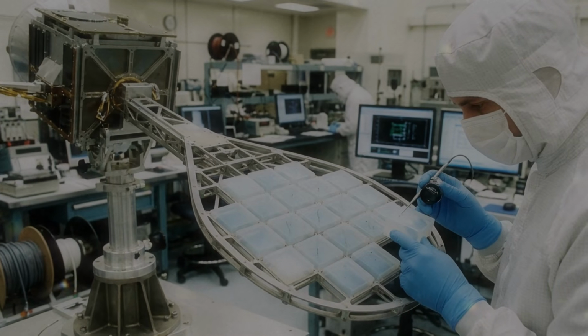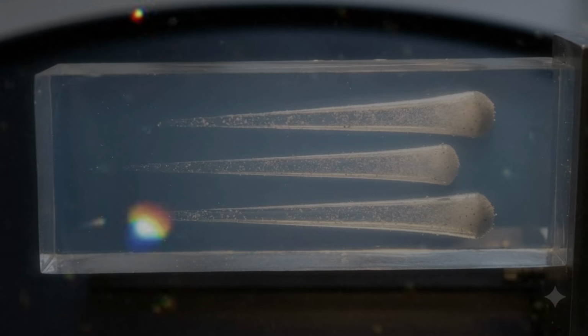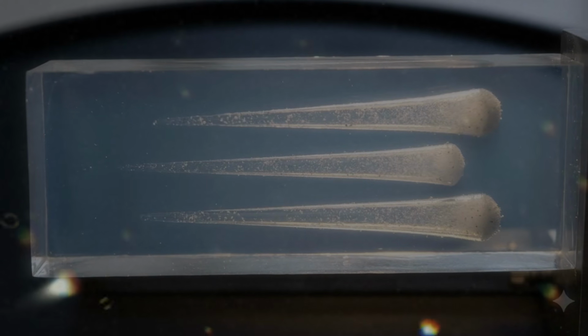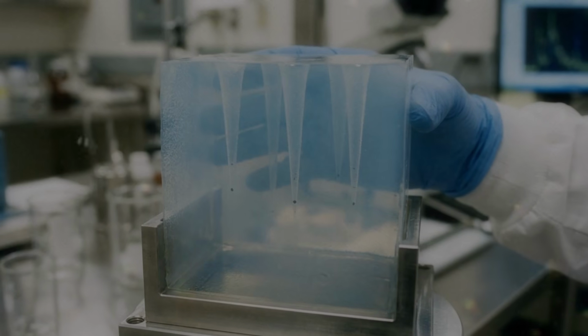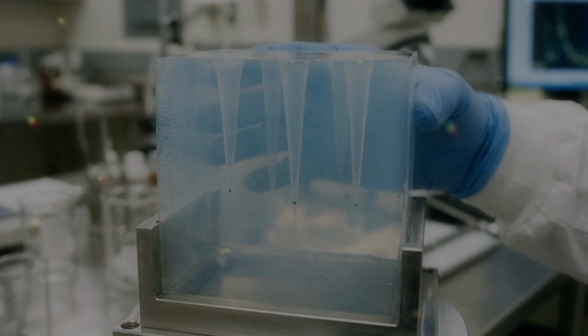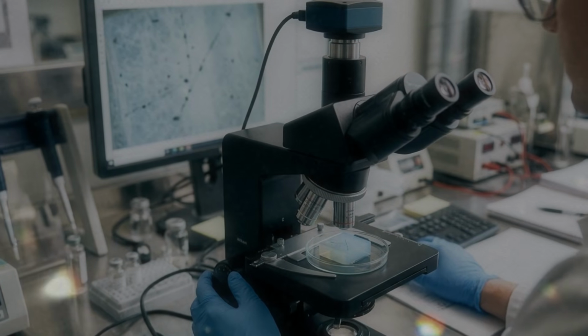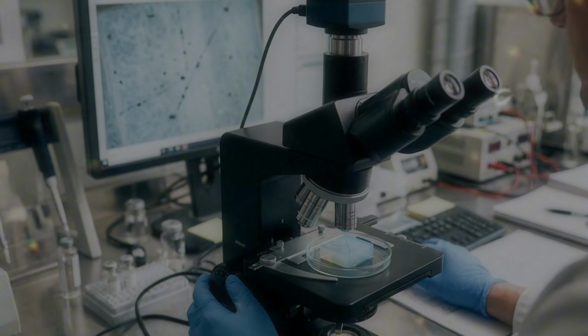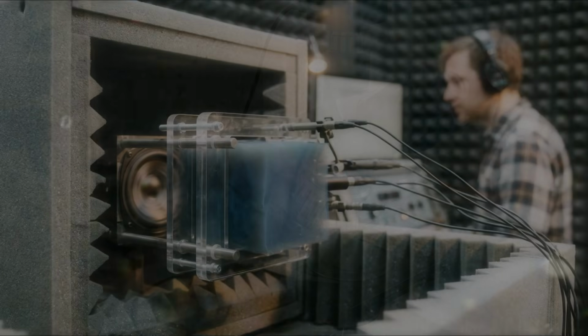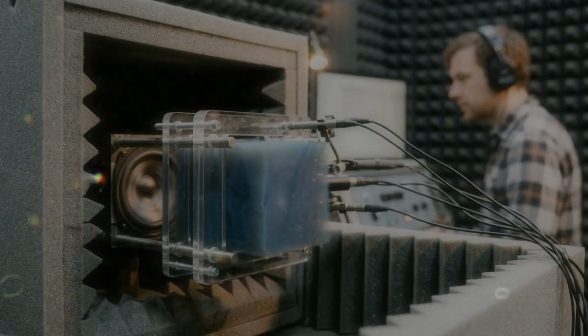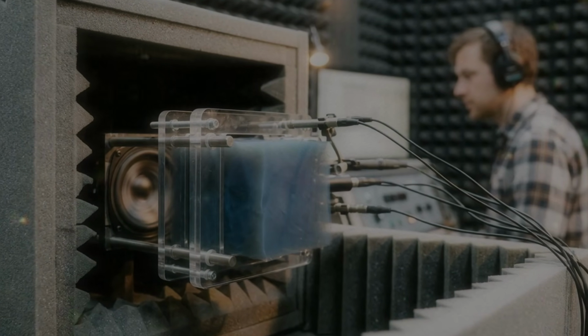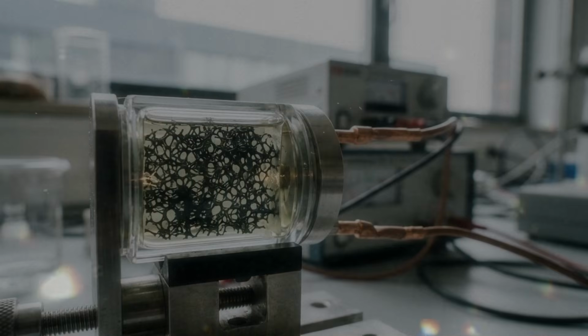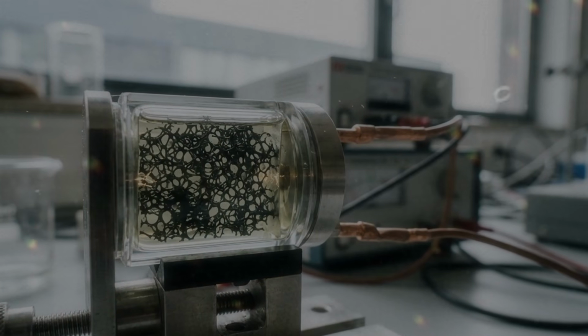Porosity tells us how much of a material consists of empty space. In an ordinary dense solid, porosity may be low. In aerogel, it can be extremely high. This does not mean the pores are perfectly empty. Under normal conditions, they contain air or another gas. If the material is placed in a vacuum, much of that gas can be removed. If it is placed in a liquid, some pores may fill, depending on how the surface interacts with that liquid. This last detail is important because aerogels can be designed to attract or repel different substances.